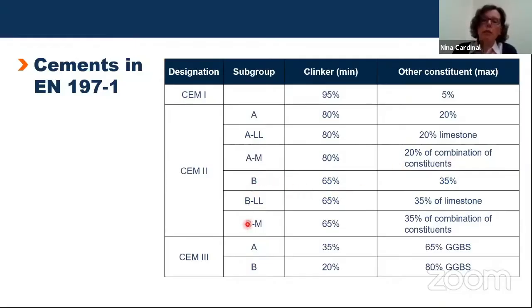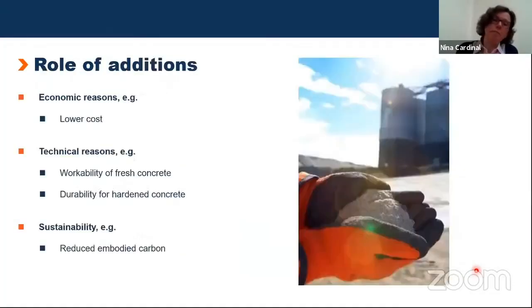The CEM2B group is built up in exactly the same way. The difference is that higher replacements are allowed. Up to 35% of the clinker can be replaced by additions. The last group, CEM3, are the slag cements, where in the group A, up to 65% can be ground granulated blast furnace slag, and in the group B, even up to 80% can be GGBS. This is how the European standard works at the moment.